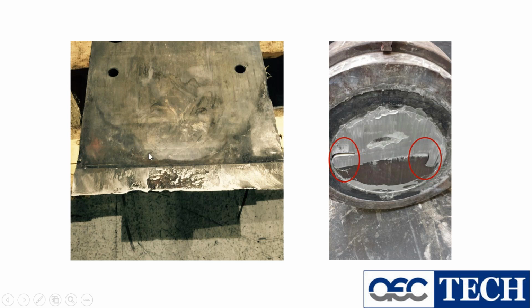When we came out with a two-piece shear blade, we didn't come out with a two-piece shear blade just so you could replace the tip. We came out with it because we know how much time it takes to shut a press down to pull off the shear blade to replace it. So what we find is that people were going longer periods of time running with a shear blade like this. But if you could take a shear blade off and replace the damaged end in a few minutes, then you're going to do it more frequently, which means unscheduled downtime is going to be kept to a minimum.